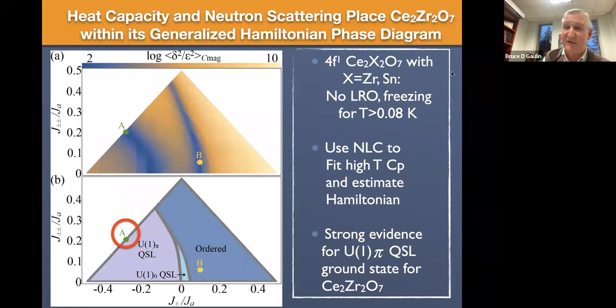So taken together, this is consistent with the original characterization, and that is, there's no evidence for long-range order. There's no evidence for freezing for temperatures above about 80 millikelvin. So this is a bona fide candidate for a quantum disordered quantum spin liquid state. It's not that there's some small Néel moment and you're thinking about that coexisting with a quantum spin liquid state. This appears to be a quantum spin liquid state on its own. We've used this numerical link cluster to fit the high temperature heat capacity and estimate the Hamiltonian. And the net result is that it's strong evidence for this quantum spin liquid ground state.